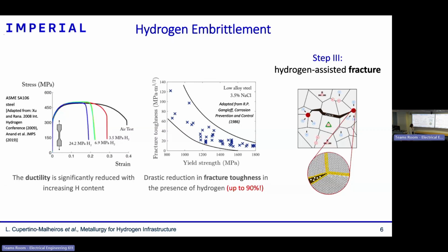And it gets so bad that for very high strength steels, you get values of fracture toughness that approach ceramic materials. So you want to design your structure with metals that are ductile, that can resist more deformation before fracture, and you can end up, depending on the environment, with a material that's very brittle like a ceramic and can crack very easily and can result in a catastrophic failure. So it's a very big problem.